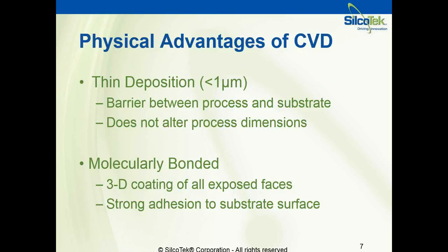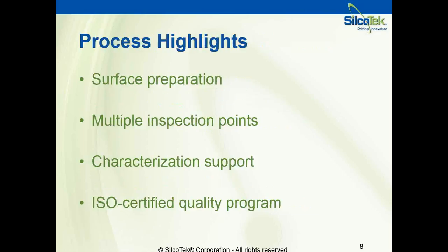So as a chemical vapor deposition layer, there are some advantages that come from that process. First, the deposition is extremely thin. Almost all of the coatings that we apply are less than a micron thick. So you have that solid barrier between the substrate and the process, but one that doesn't alter the dimensions of the parts or force a redesign once parts are coated. The coating is at the molecular level, so it's actually physically bonded to the base substrate, which creates essentially a new surface. So it's a three-dimensional coating that all exposed faces will see. And again, the coating is very strongly adhered to the base substrate below.